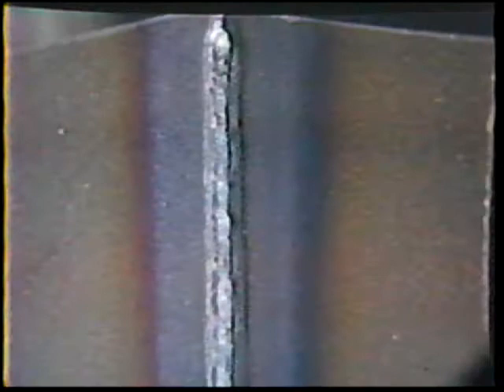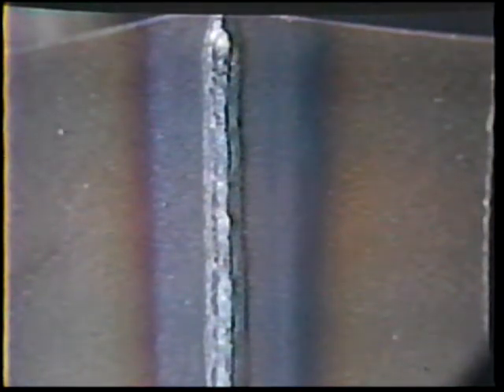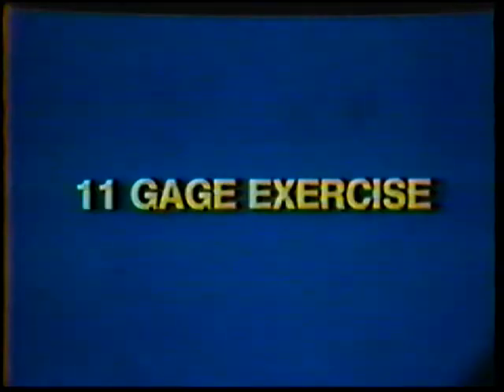The finished weld will be even, slightly convex, and 1 electrode diameter wide. A small bead will have formed on the back side for full penetration. For the next 2 exercises, prepare a workpiece with 2 11-gauge pieces tack welded at each end.